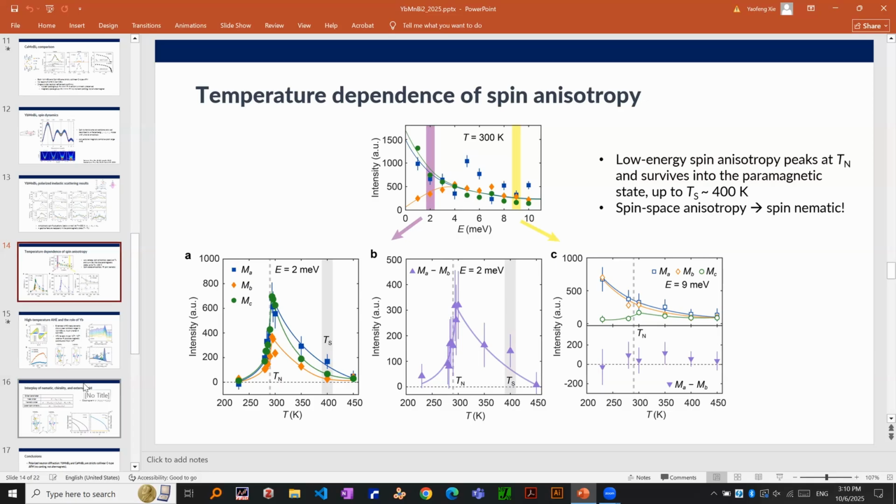I have a question. Some of these compounds are known to have a little bit of orthorhombic distortion, like calcium manganite. Can you rule out any possibility of a little bit of distortion in the structure? I guess we tried many different methods, both polarized and unpolarized, and single crystal neutron refinements. Within our detection limits, we don't see any orthorhombic signatures. There is no evidence of it.